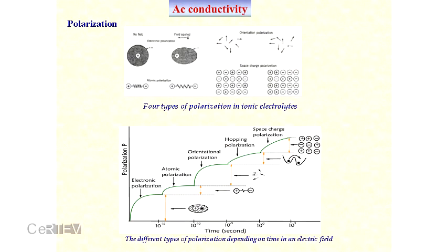Here is the most general picture in a wide spectrum. If you consider a wide spectrum, what would be the different types of polarization we meet? You have this picture in textbooks. In this region the time is very short, and here the time is very long. Otherwise, the frequency is very low here, and in this region the frequency is very high. If you go from high frequency to low frequency, we get different types of polarization: electronic polarization, atomic polarization, orientational polarization, where the dipoles can change their orientation, and hopping polarization. In this region an ion can hop from one position to another, and there is space charge polarization.